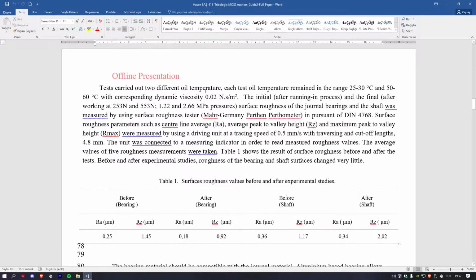Tests were carried out at two different oil temperatures. Each test oil temperature remained in the range of 25 and 30 degrees centigrade and 50 and 60 degrees centigrade, with corresponding dynamic viscosity 0.02 Newton second per square meter. The initial load after the running-in process and the final load after working were 253 Newton and 553 Newton.